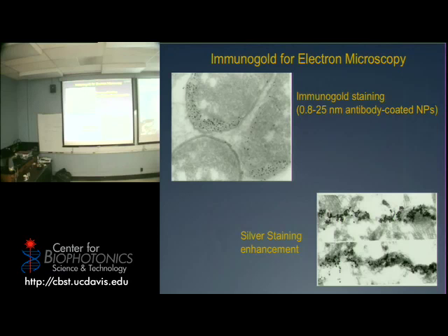Have you guys talked about transmission electron microscopy or anything like that? No? So essentially, it's like a normal microscope, but in this case, rather than having light in the visible, you have electrons that go through a sample. It has to be really thin because electrons are absorbed, and essentially they pierce through and get scattered according to the density of the medium they go through. And if you have a heavy metal like gold, obviously they get absorbed much more.